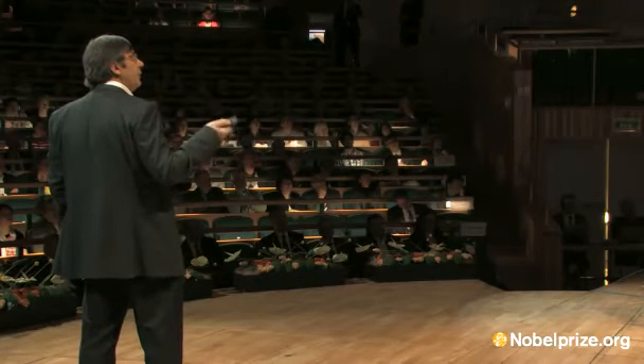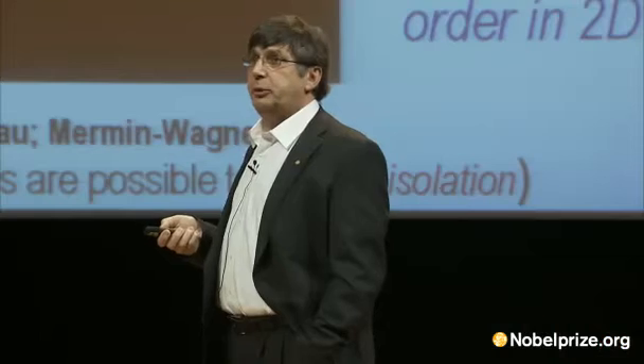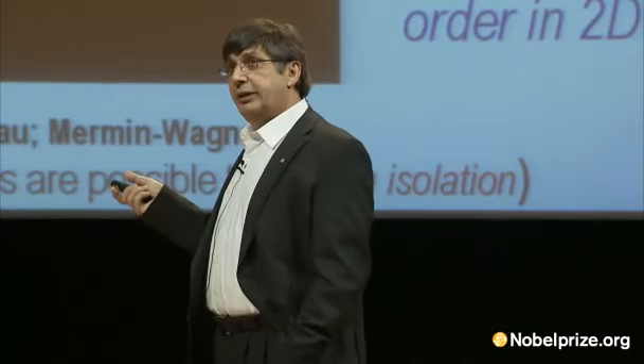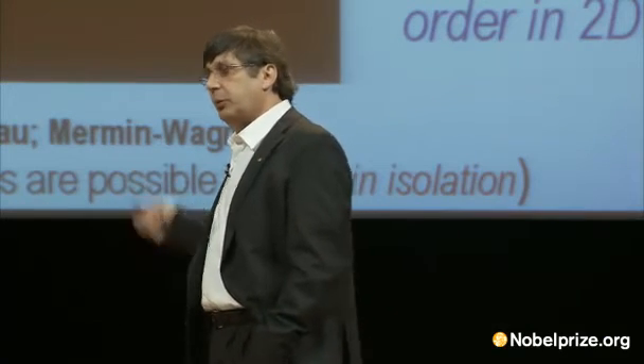I also knew another argument that comes from Mermin-Wagner's theorem: in order to grow anything, you need a temperature close to the melting temperature, and at this temperature, vibrations diverge in 2 dimensions, not in 3 dimensions, and everything goes 3D. So essentially, 2-dimensional growth, unless you do it at very low temperature, is completely forbidden. And sometimes people misuse this theorem, applying it to graphene at room temperature. You have to apply it at the growth temperature.